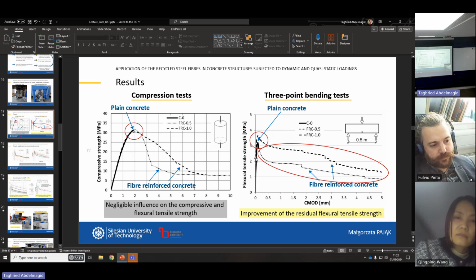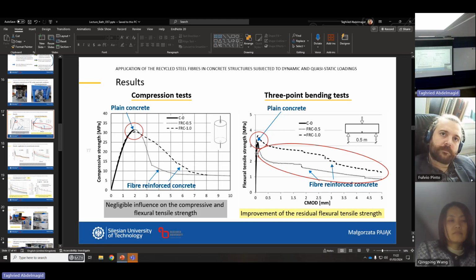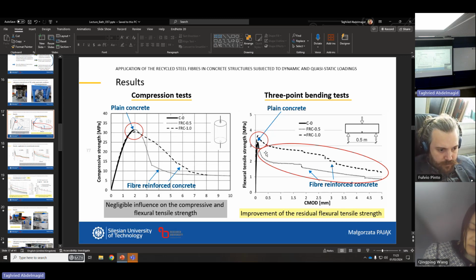first crack strength. So it's impossible because, you know, for concrete, with very little strain, the concrete is crushed. And the fibers don't know that there is some strain, because of the differences in the modulus of elasticity. So all the fibers act the same. They start to act after the cracking of the concrete, and then it is connected with the process of bridging and so on. They all act exactly the same way.